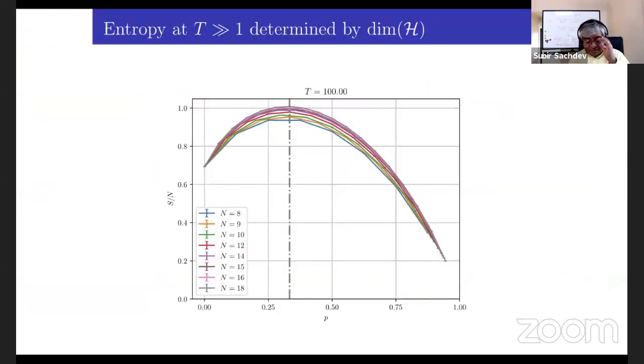Okay, so another thing that Henry and Alex have done is compute the entropy. So this is the entropy for various system sizes as a function of doping. Now, depending on the system size, we can only have certain rational values of doping because the system size is small. So there are a lot of different rational points here, but they average over, I think, many hundreds of samples. And certainly at very high temperatures, T of 100, the entropy has a maximum, again, exactly at 1/3 in this case, because that's where there are the most states available, which is, I think, closely related to the fact that the spinon and holon states have the same chemical potential.